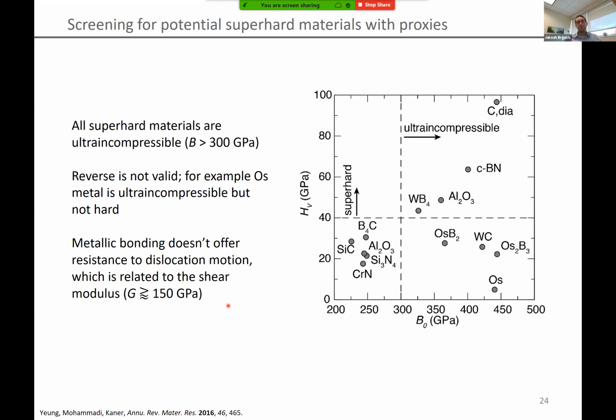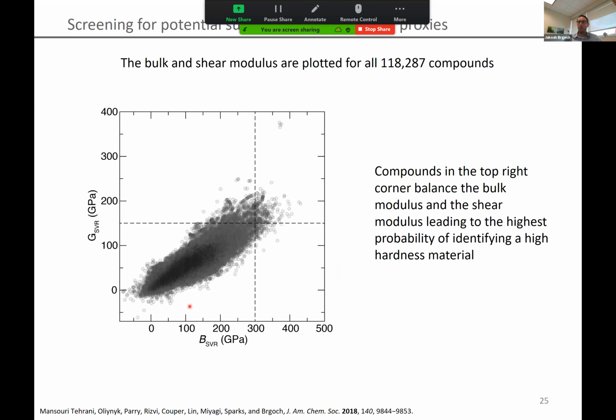Think back to my introduction slides—shear modulus was related to hardness nearly linearly, and that's related to the material's dislocation motion. There's no clean cutoff for shear modulus and dislocation motion, but analysis of different types of high hardness materials suggests anything above about 150 gigapascals for the shear modulus should be okay. So what we can do now is take this plot of 118,287 compounds.